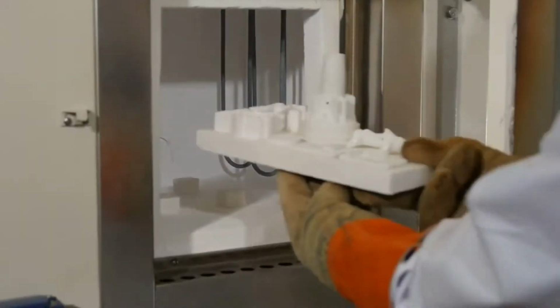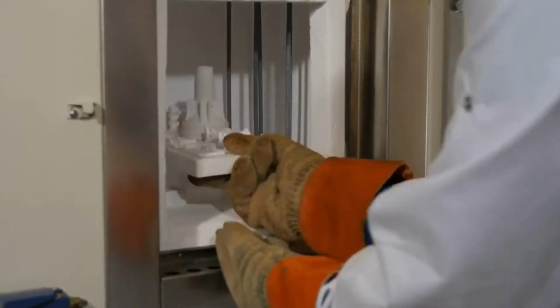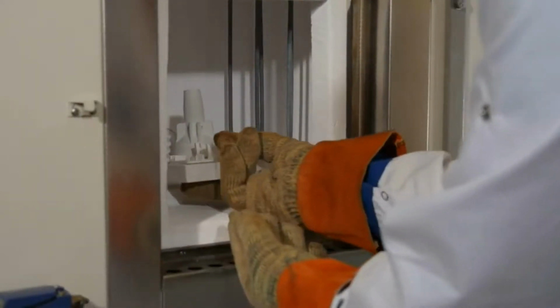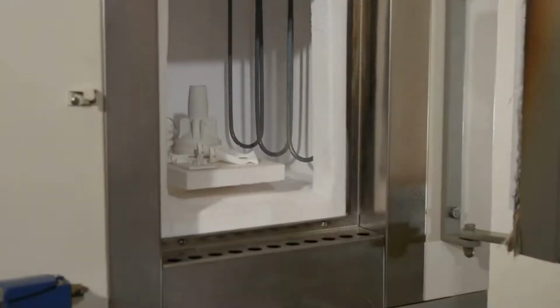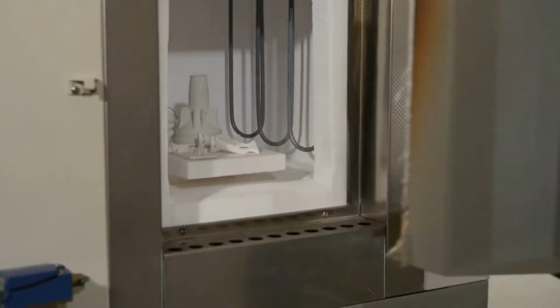After shaping, the ceramic parts are sensitive to any changes in their surrounding parameters. This is inherent to the ceramic material: moisture, temperature, pressure, support, storage. These parameters have to be controlled and mastered to limit the development of excessive internal stresses from which cracks and potential defects will result. The drying stage is not too complex and long thanks to the use of organic additives less sensitive to the environment.